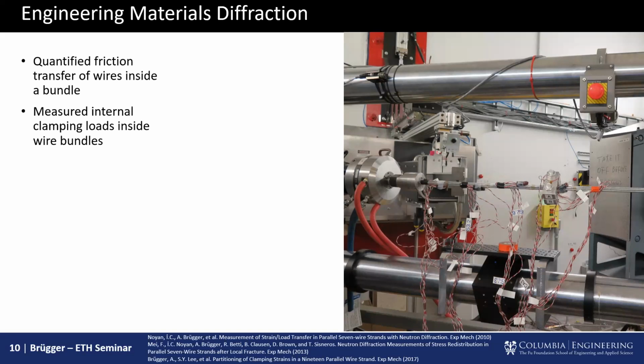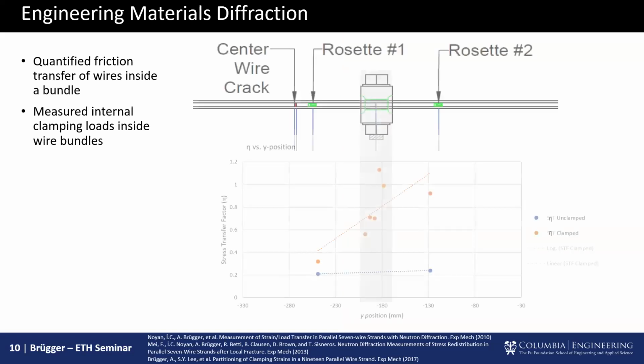So what we did here is, you can see the wire strand here in the diffractometer. We essentially broke the center wire, then under various confinement loads with a clamp, we actually measured the load pickup of the center wire through that clamp. So we now have essentially a friction coefficient as a function of confinement through that clamp. So that was step 1.